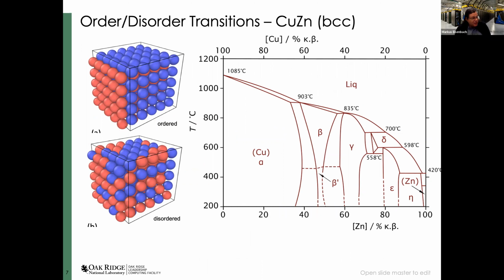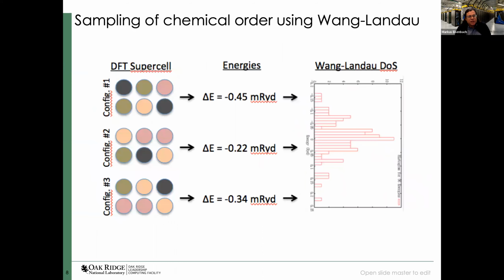So, another example here is to look at order-disorder transitions in alloys. An example here is the copper zinc system, particularly the 50% copper, 50% zinc BCC system, where we have a transition from an ordered to a disordered phase, so beta prime to beta, at around 500 Celsius. So we want to see if we can describe this completely from first principles, and to do this we used the Wang-Landau sampling method,